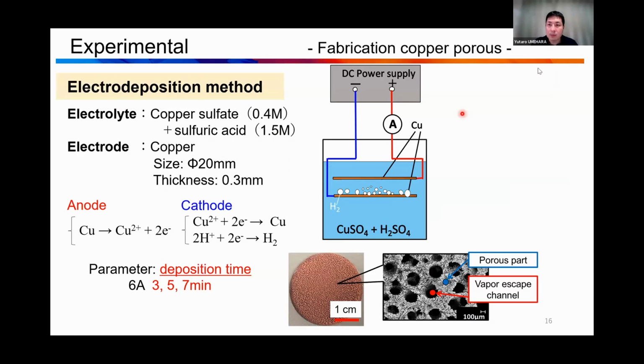So this is how to make the copper porous plate. We use an electrodeposition method. This is usually a plating method, when we cover a metal with a layer of the same metal. In the usual plating case, they apply a very low current, but in our case we applied a very high current. So finally we get hydrogen bubbles from the cathode and the anode like this. The copper flake is deposited on the surface, and hydrogen bubbles also come out from this cathode. And then finally, we get a kind of copper porous plate.